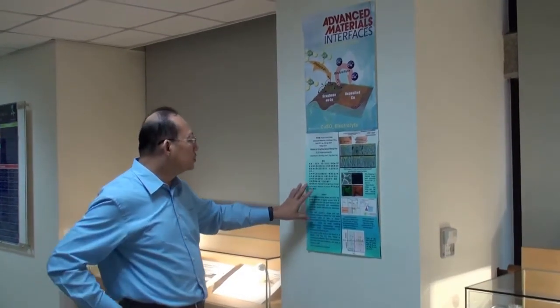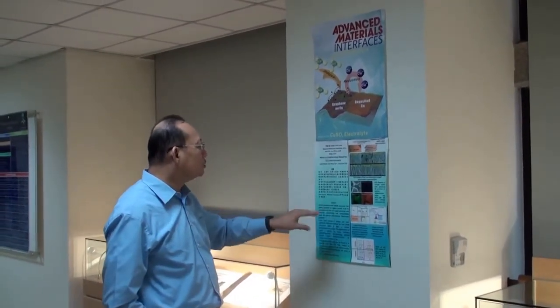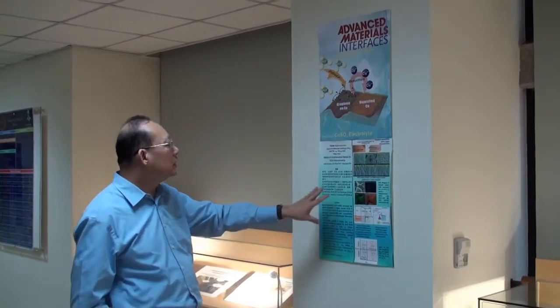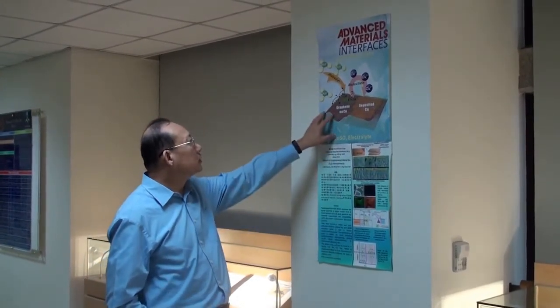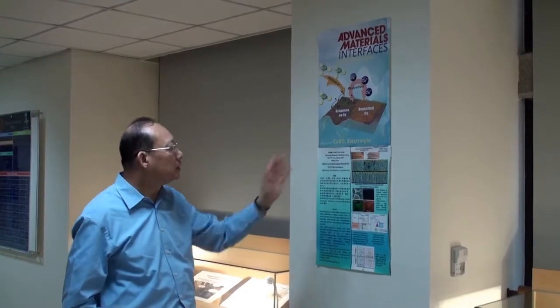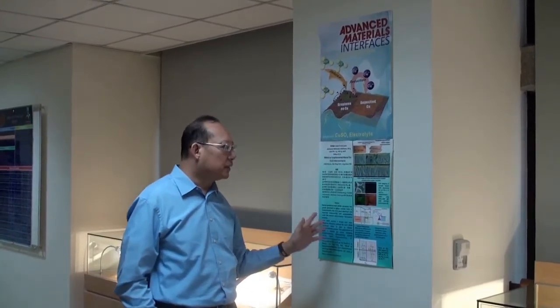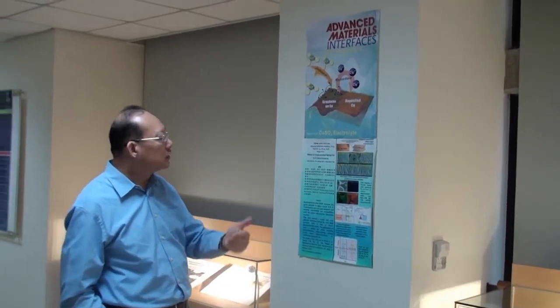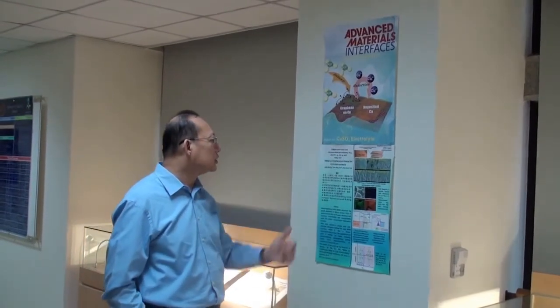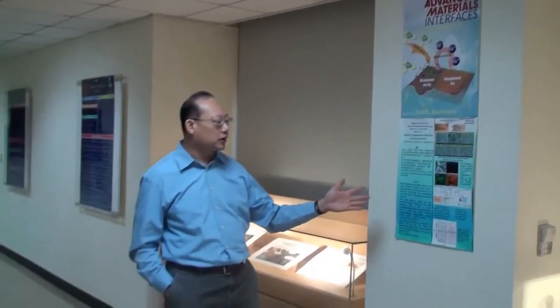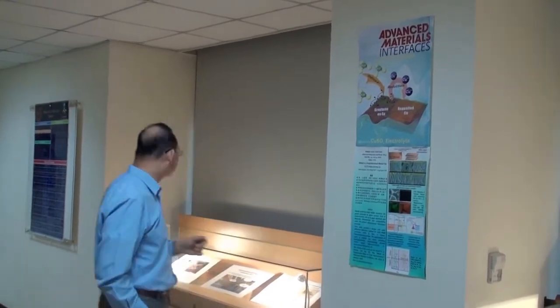Now, we discovered a new method of how to put the graphene into the copper, and this paper was submitted to Advanced Materials Interfaces and became the cover page. And this method is so simple: you just immerse the first copper layer into a copper sulfate electrolyte solution, and within a few minutes you can form graphene on top of it, followed by the deposition of the copper. So this is work that has actually interested TSMC to explore further.